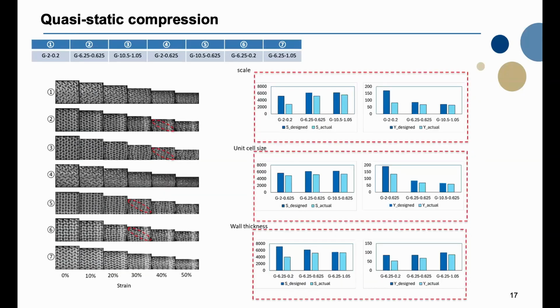And this is the quasi-static compression. As we can see, some lattices have a shear band after compressing to certain strengths, and some of them don't. This is related to stretching-dominated and bending-dominated behavior. And if we compare the stiffness and the yield strength of the actual lattices to the design, we can see the deviations for the lattices with the smallest dimensions, and all of these deviations are caused by the geometrical inaccuracies.